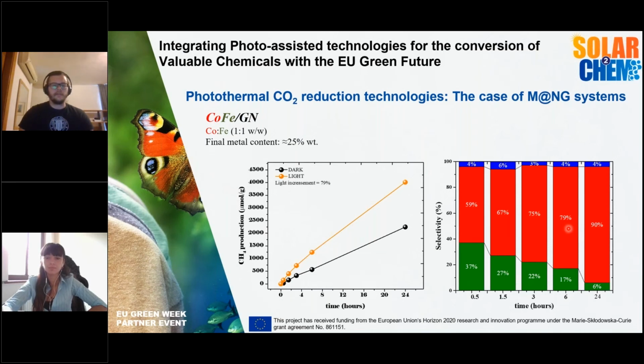Jumping right into the catalytic output of these materials, when we consider cobalt iron, a system that has been investigated quite a lot in the past years, at least in CO2 reduction, the catalytic output is good. In 24 hours, we can achieve around 40% conversion. What's very interesting to note this time around, since the technology is already well known, is the light enhancement. This is the main objective of photothermal studies, at least from a fundamental point of view right now. The light enhancement is around 80% compared to the dark conditions, which is quite significant.